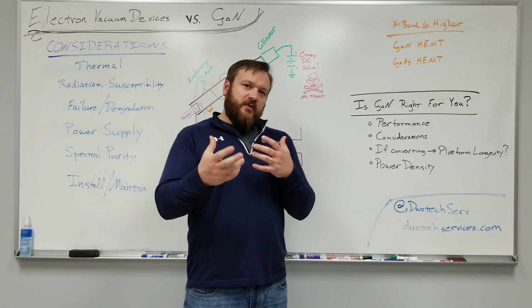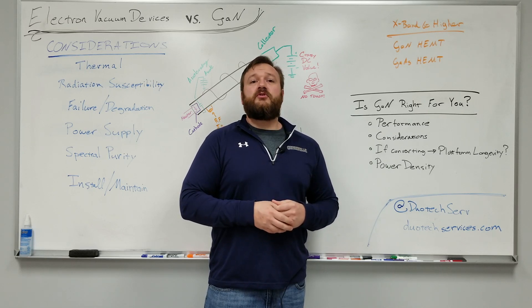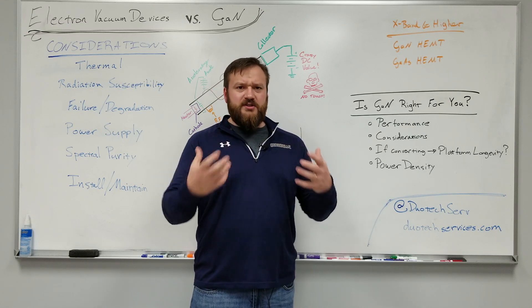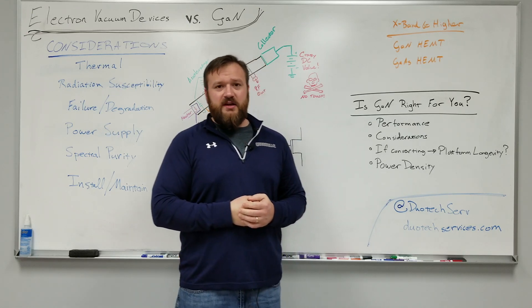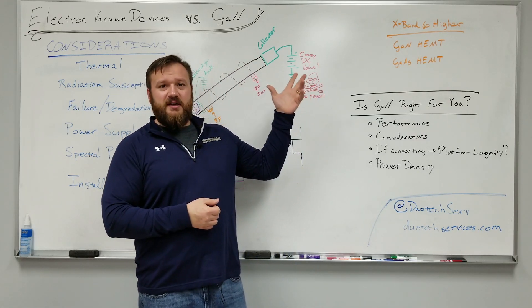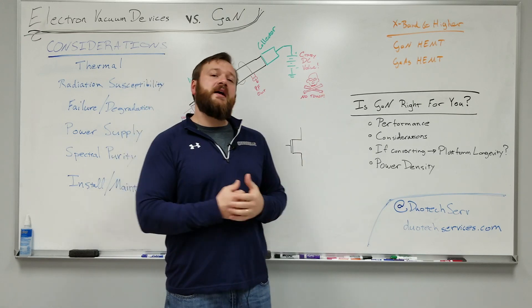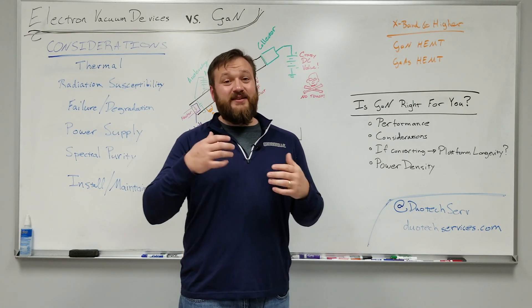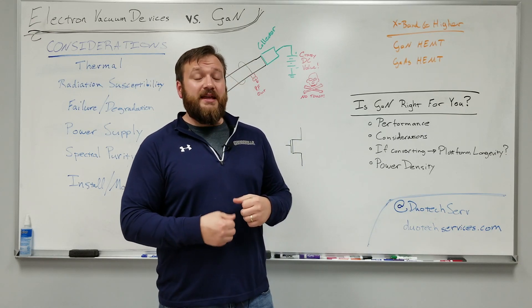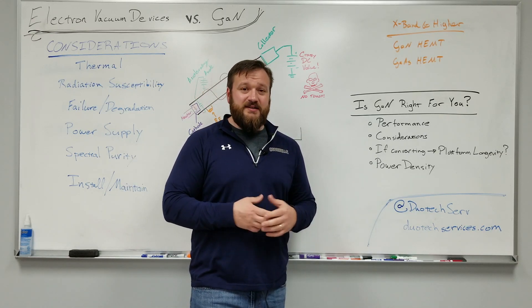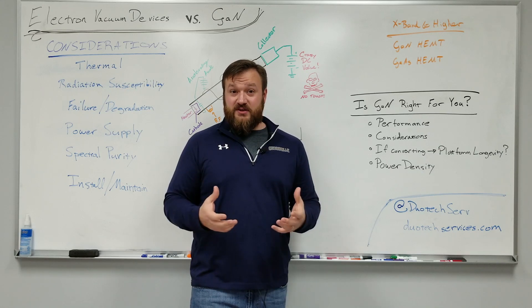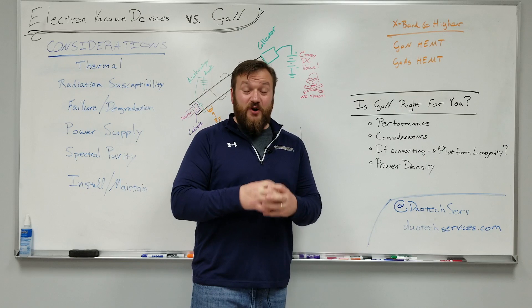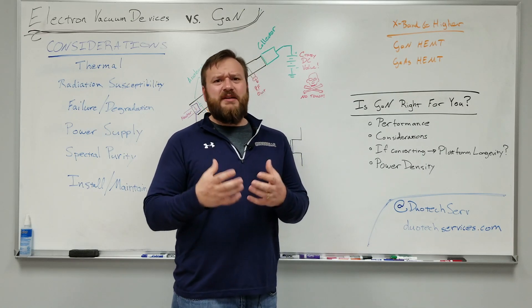The band of operation we're thinking about for radar is primarily X-band and KA-band, and that really lends itself to gallium arsenide and gallium nitride. For power density, gallium nitride on silicon carbide is particularly well-suited — getting the heat out and achieving good power densities. As device power densities rise to 300 watts and 300-watt-plus devices per transistor, we're talking about a great deal of power density.